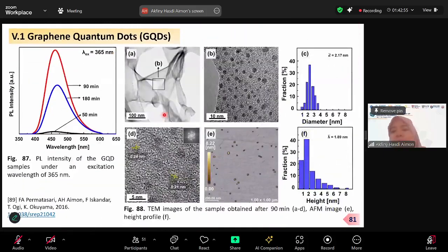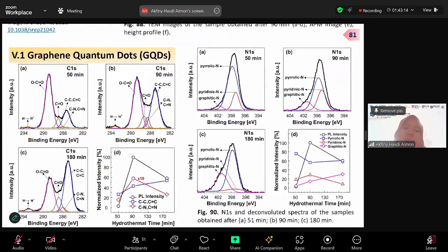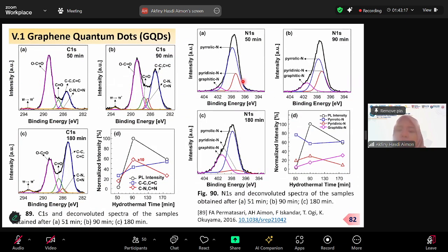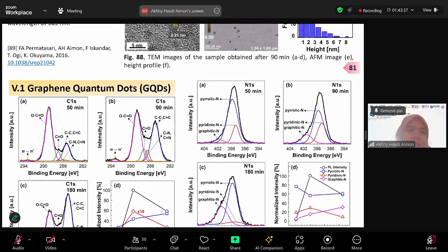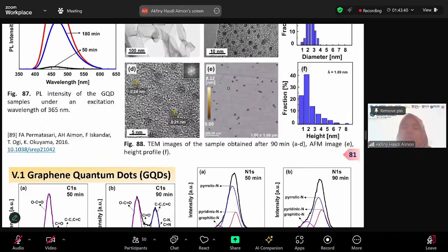And this is the TEM image of the sample and also the AFM image of the sample, and the profile of the sample. You can see here the dots, the quantum dots, also here in the TEM image. Here is the distribution of the bonding between pyridinic and graphitic in your sample based on the hydrothermal times. We did 50 minutes, 90 minutes, and 180 minutes. Sorry, I mean here it's in minutes. So it's quite fast.